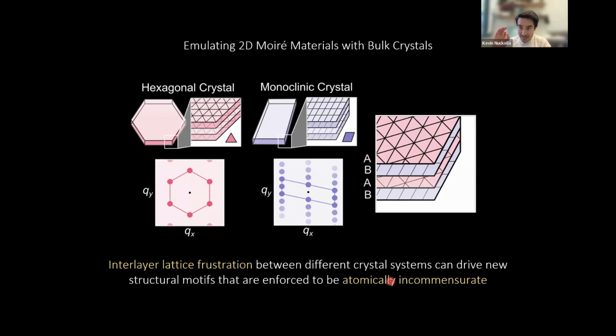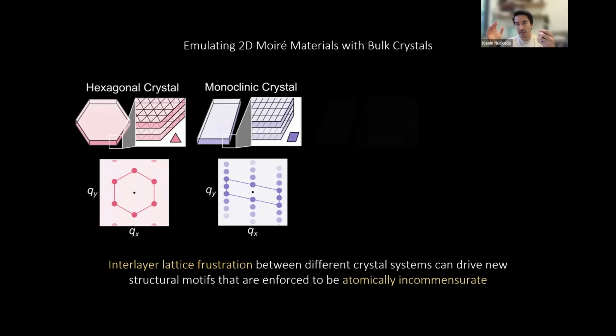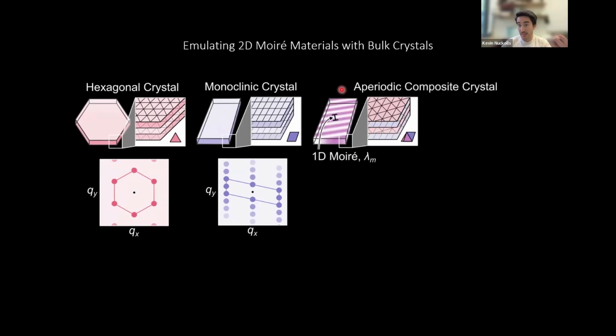What the misfits didn't give us was the fact that these misfit compounds are typically hexagonal transition metal dichalcogenide layers with cubic rock salt layers, like lanthanum sulfide or lead selenide. These cubic layers have very different symmetries than the hexagonal layer, and they have very different lattice constants. And so they don't couple in interesting ways that morph the structural modulations of the hexagonal lattice. But here, monoclinic crystals and hexagonal crystals are much closer in symmetry, and we'll choose ternary phase diagrams where we can find lattice constants that are very similar. Because of similar symmetries and similar lattice constants, these superlattices will want to relax into new Moiré superlattices in bulk crystals.